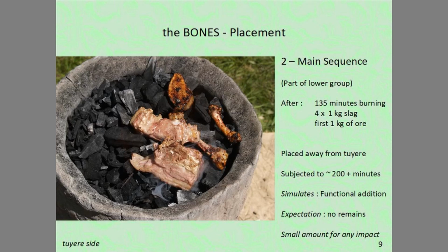These bones would be subjected to approximately 200 minutes of high-temperature burning time. It was felt that this simulated a functional addition of bone in an attempt to modify the process of the smelt. Our expectation was that there would be no physical remains from this addition. It should be noted that a potential experimental error again is that this is a very small addition of bone if the expectation was to impact the smelt itself.